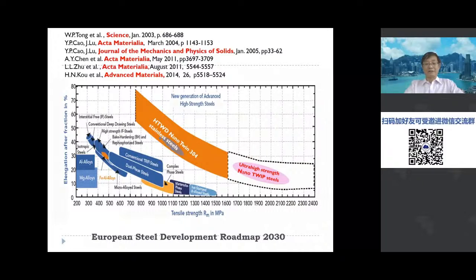So if we plot all our results on the European Steel Development Roadmap 2030, 10 years after, you can see the material we obtain are already inside of the target of this European steel development. And also with ultra high strength nano twin steel, our mechanical property is even better, out of this zone defined by the European steel development roadmap. So that means it's possible to have high strength, high ductility material in different variety, and we just need to manage at the nano scale the nano twin, and with high density nano twin.